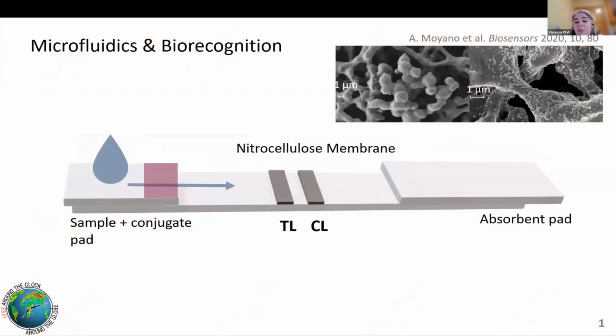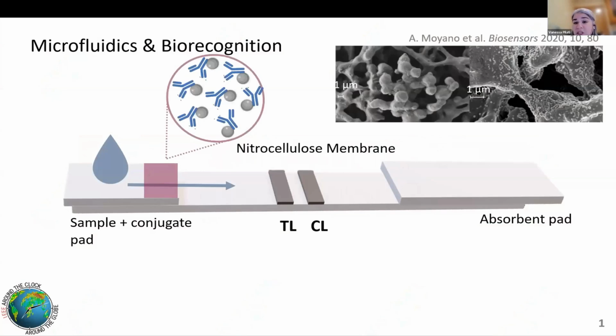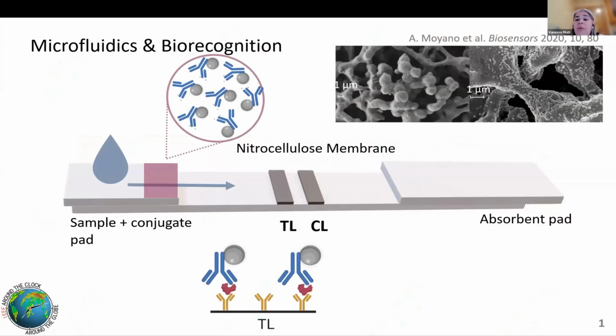The lateral flow assays are based on microfluidics and biorecognition. We have a paper device. We deposit some drops of a fluid to analyze in the sample and conjugate pad. In the conjugate pad, we have some biorecognition molecules that can capture the analytes together with a nanolabel or a nanobead or microbead to be seen. This system will flow by the pores of the nitrocellulose membrane until it finds the test line. In the test line, we have other biorecognition molecules that can capture the analytes together with the nanoparticles. The rest of the fluid goes on until the control line, where we have other biorecognition molecules to ensure that the test worked properly.